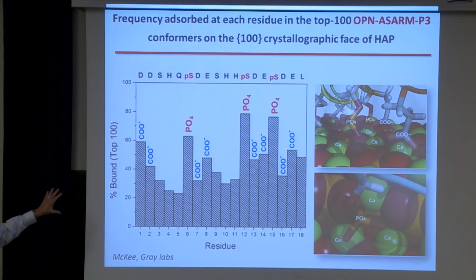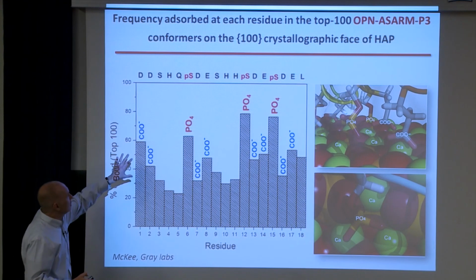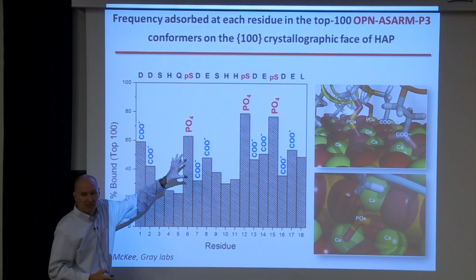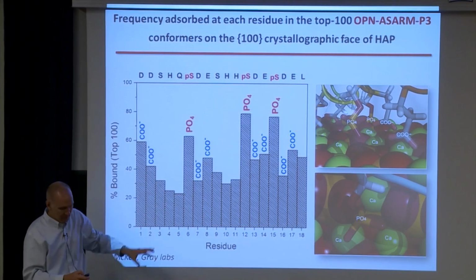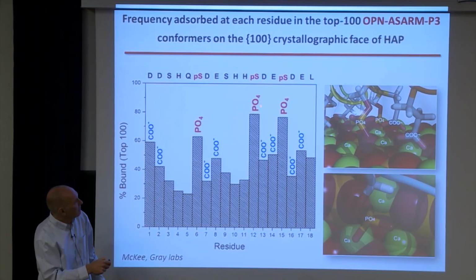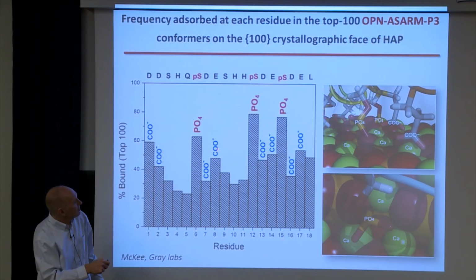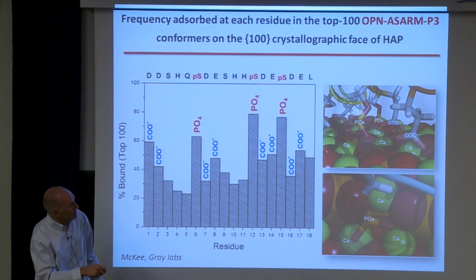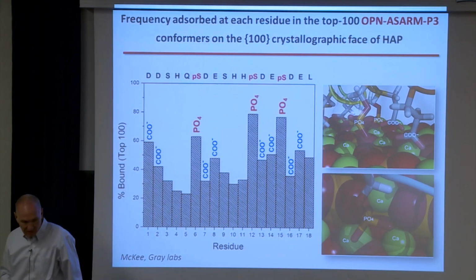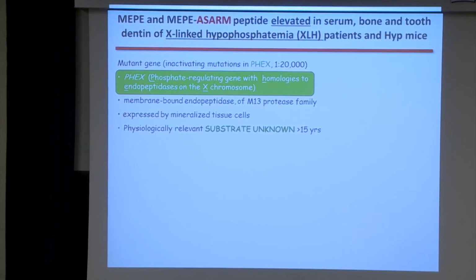And from those top 100 scoring models, you can go in and find out which amino acids in your peptide were closest to the mineral surface, and it was always the phosphates and the carboxylate groups in these very acidic peptides which were coordinating with surface lattice calcium. All right.